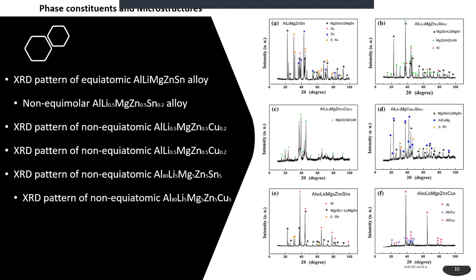Okay, now looking at the phase constituents as well as the microstructure in a typical material, Zhang and his team in 2015 characterized six aluminum-based high entropy alloys. Among them is one equiatomic and five non-equiatomic alloys, as you can see. The XRD of each of these alloys is given in the view graph, and the major phases have been identified. I'm just going to talk about the first alloy and the XRD pattern of this equiatomic alloy, which we can find in the first figure, figure A.